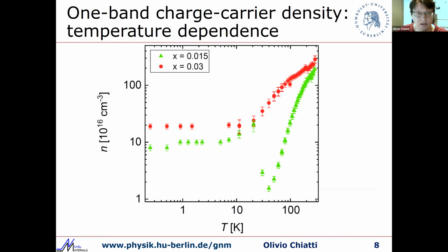If you look at the results of the Hall measurements and we calculate a one-band charge carrier density from the Hall coefficient, we see that this carrier density decreases with temperature until about 20 or 40 Kelvin, like we expect in a semiconductor, and then it saturates at a constant value, which is what we would expect from surface states like topological surface states. What we didn't expect is the minimum in the charge carrier density of the sample with lower vanadium concentration. We're not sure yet why this happens, but we can see that it still saturates at lower temperatures.